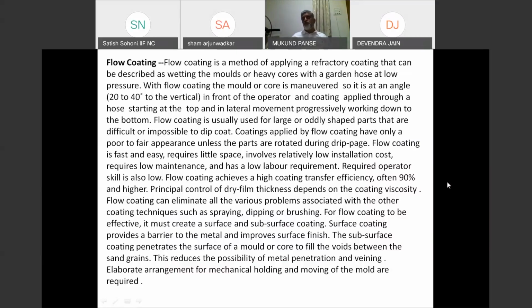If such a big mold you have to paint by brush, you will take a very large time. Also the transfer efficiency. If there is a certain quantity of refractory in the coating and you check after the coating is applied how much refractory actually goes into the mold or core coat, by flow coating it is the maximum because it is very fast and you can have whatever thickness of coating, other than spraying or dipping. The process has to be standardized, but mainly used for very heavy molds, normally not used for smaller molds.